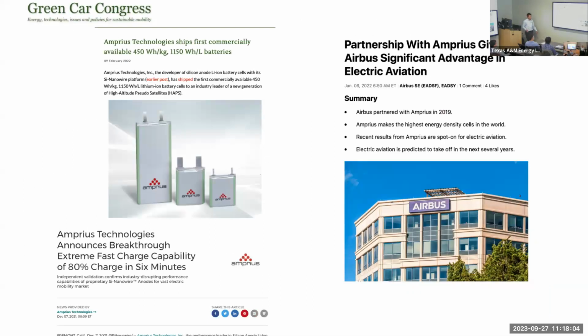We also demonstrate that silicon can do fast charging, much faster than graphite. Graphite cannot. Six minutes to 80%. This is a huge breakthrough, fast charging in addition to high energy density. The reason is that silicon, once you put lithium in, becomes amorphous, a three-dimensional structure lithium can come into. Not only that, its potential is slightly above graphite. This provides a safety margin in voltage. If you do fast charging, silicon's potential does not go down to the metallic lithium plating potential, making it very safe. So silicon could do that.